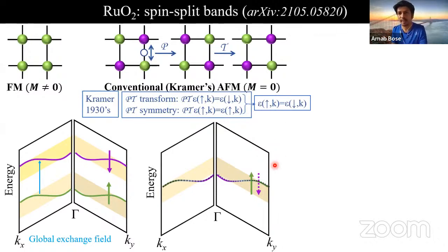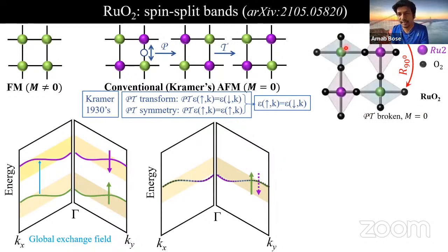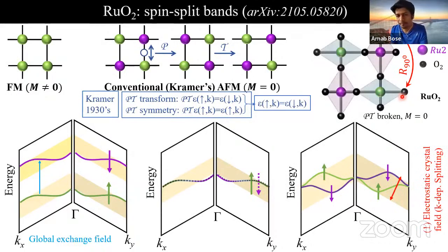Now let's have a look at what happens for ruthenium dioxide. These green and purple color balls refer to the ruthenium atoms having up and down spins, and black color balls refer to the non-magnetic oxygen atoms. If we ignore these non-magnetic oxygen atoms, this looks exactly like the classical collinear antiferromagnet I just discussed. But the moment the oxygen atoms are considered, immediately it breaks the PT symmetry and we have 90-degree rotational symmetry. Since the PT symmetry is broken, it is now allowed to have spin split bands, even though the net magnetization is 0, as theoretically predicted in these papers.